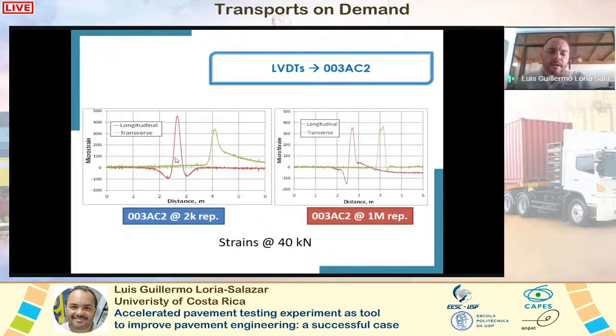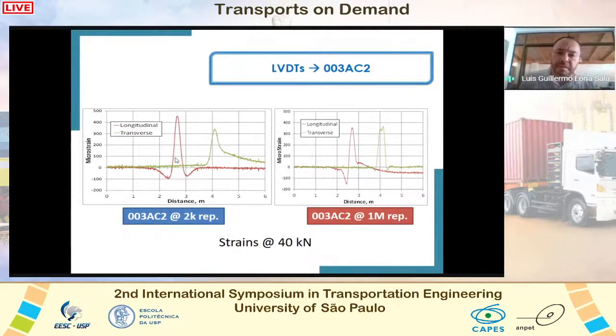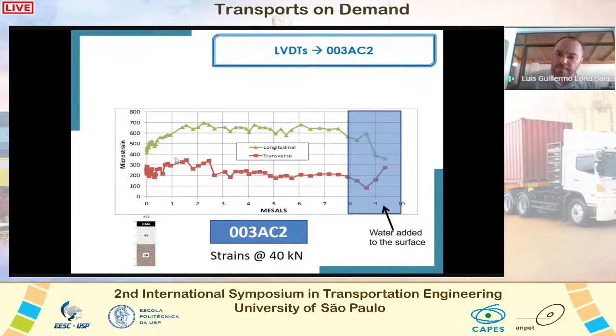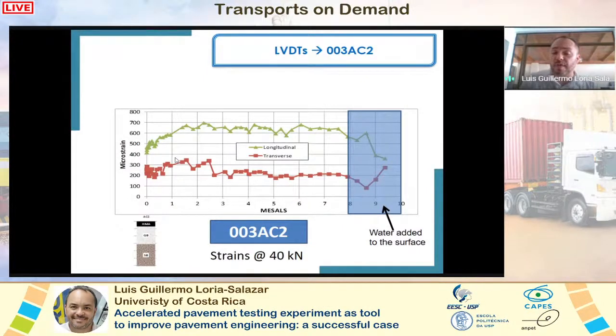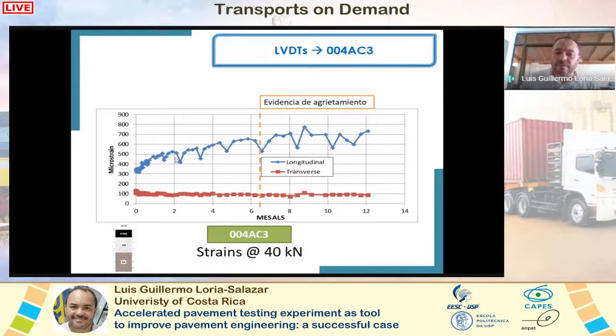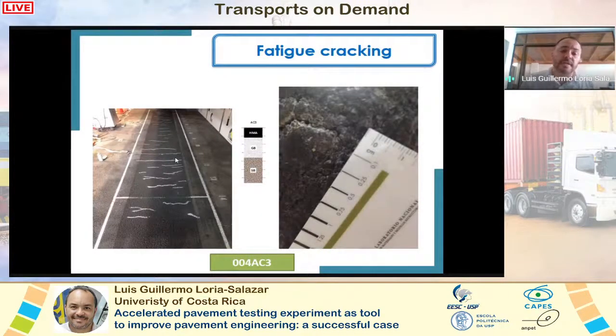Well, just a picture of how the strains are measured by the LVDTs in the longitudinal and the transverse directions. It was expected theoretically. And also on the right-hand side, you can see what is happening when the material starts having damage. You can also see the microstrain, the strains on the bottom of the HMA layer, and how it starts behaving weird when we put water at some time of the experiment. The idea is that we realized that if we throw water on top of the pavement surface, you can see the cracks better with time. The same happened here. You can see the longitudinal strain start picking up when you start seeing the cracking of the pavement. Here you can see the cracks, basically horizontal. After that, longitudinal ones also developed, and you can see over there a measure of the cracks.